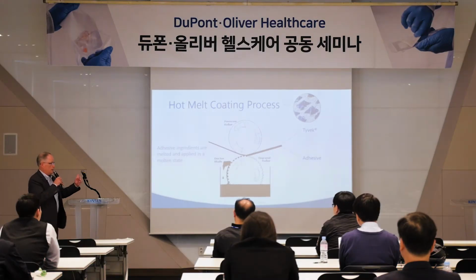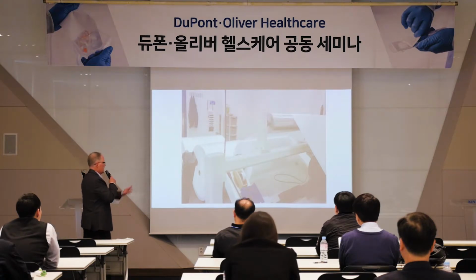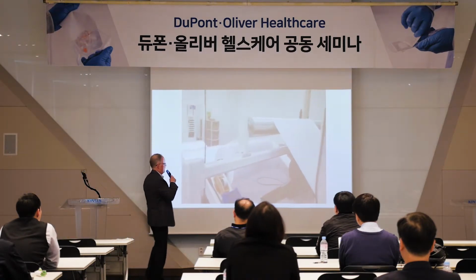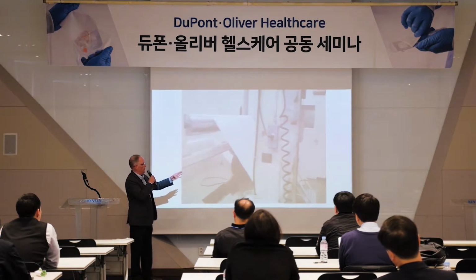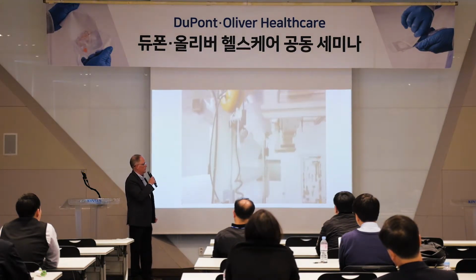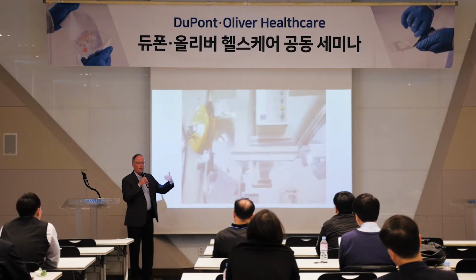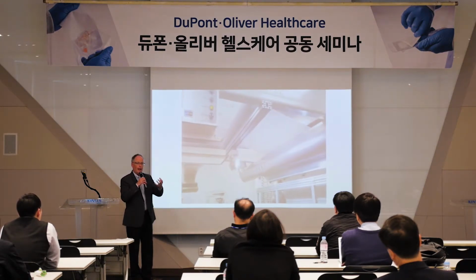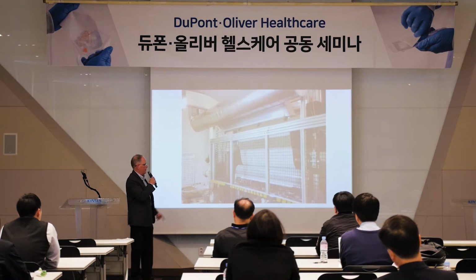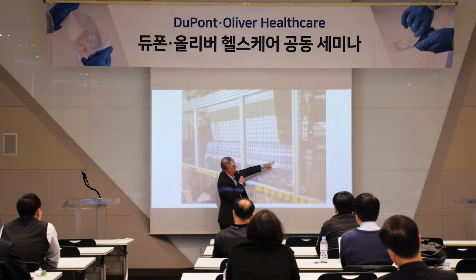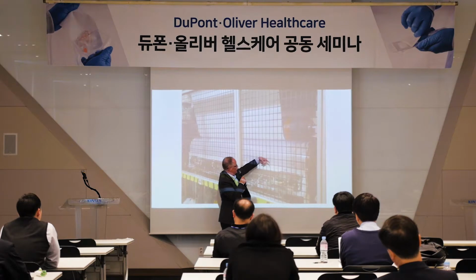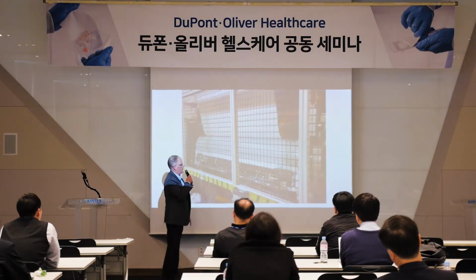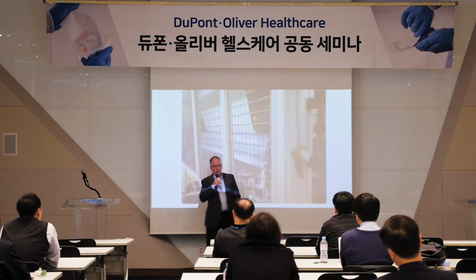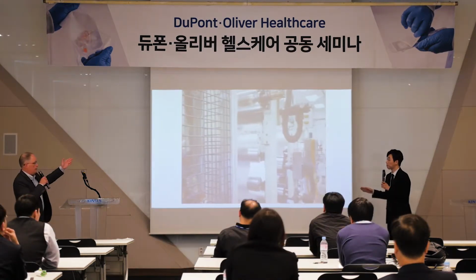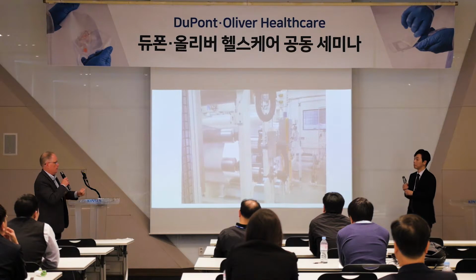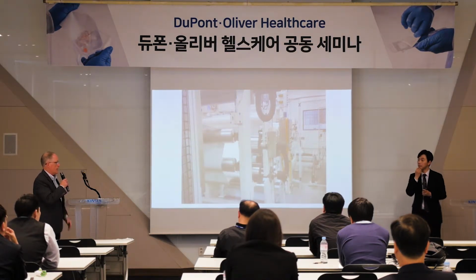So the next will be a video of the same process. You'll see the master rolls of Tyvek, and really the magic is all going to happen at the interface. You'll see a silver cylinder where we're applying the molten adhesive. The adhesive is going to be hot, controlled at about 300 degrees Fahrenheit, and applied right at that interface. This cylinder is rotating and applying the adhesive right there. After it's applied, it hits a chill roll to cool it down, but prior to that, it's at high temperature.